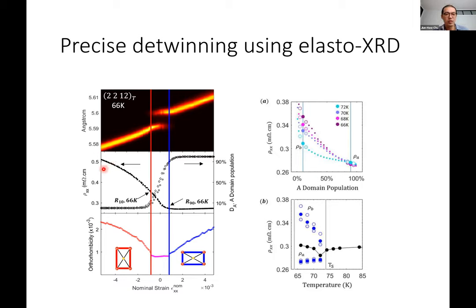So you can see that even if we fully detwin the crystal, it's very hard to tell from resistance alone that we have already detwinned the crystal, especially in this region, where the resistance is basically a very smooth curve. So it's only with the help of X-ray diffraction that we'll be able to know that we're only detwinning the crystal, but not actually further distorting the crystal lattice.